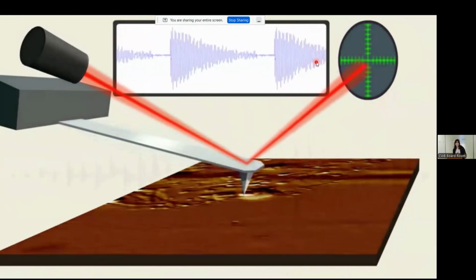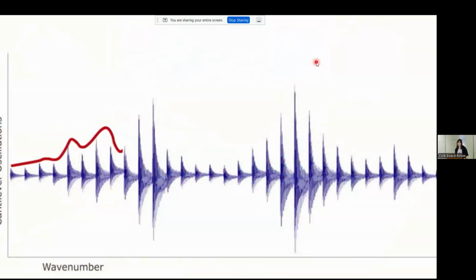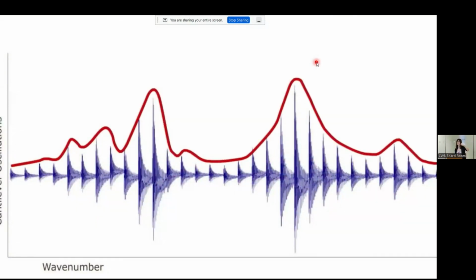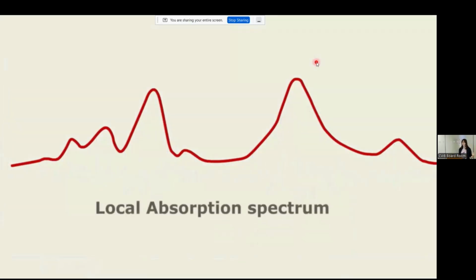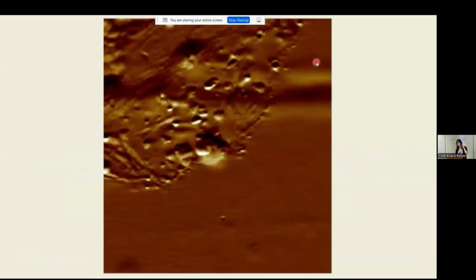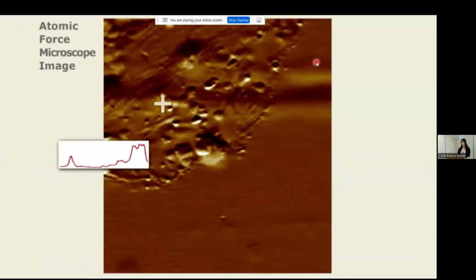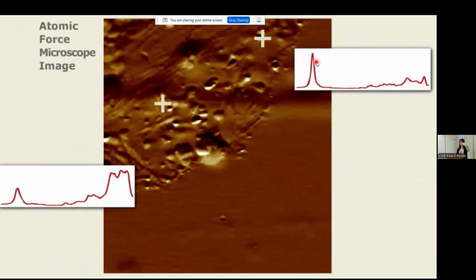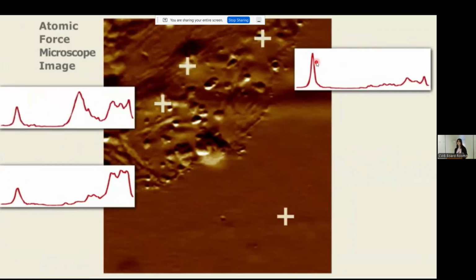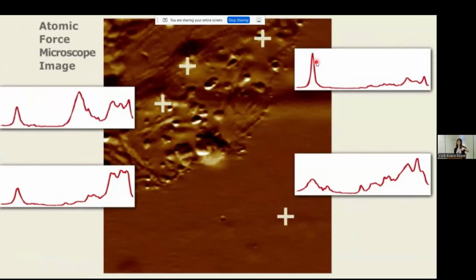So we're now taking that in, and then we'll look at the spectra. You're going to change the wavelength of the light that you're using, and you're going to measure the wobble at every single wavelength. Through that, you get a measurement of the local absorption spectrum just beneath that AFM probe. Now we can look at these different areas on the sample, and you can see how they all have distinct chemical natures, far beneath what you would see with infrared spectroscopy alone.